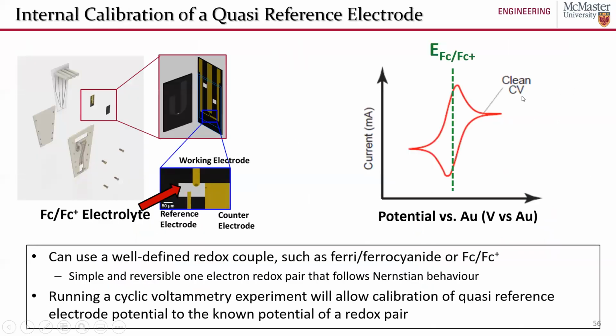Another way to calibrate a quasi-reference electrode is by an internal calibration. And you can use something like a ferrocene-containing electrolyte or a ferrocyanide-containing electrolyte. And those two couples that I mentioned are essentially simple and reversible one-electron redox pairs. And when I say reversible, it means they don't have high overpotential when they switch between the Fe2+ and the Fe3+ state. So you can insert your ferrocene-containing electrolyte into your microchip reactor, run CVs